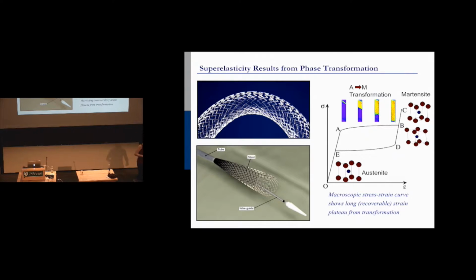So we'll come back to that. But here you start in the B2 cubic austenite. You load up. You pull your sheet. This purple is the low strain. This is the austenite. And this yellow is the martensite that nucleates. And it's almost like a Lüders band. It propagates through the material in a very highly localized strain pattern. So here you've got 0% strain. Here you've got like 6% strain.